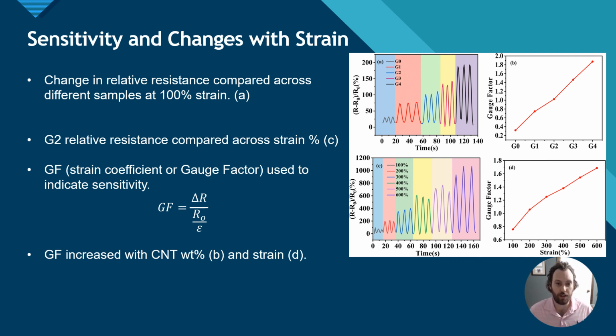This was first done by calculating a relative resistance of the polymer and eliciting an amount of elongation to the different polymer samples, first at 100% strain. You can see here listed in A the different polymers at different strain at 100% strain and the comparison of their relative resistance.